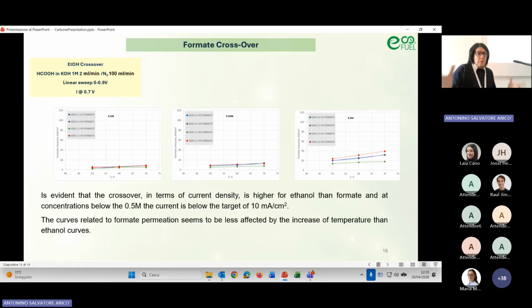Because some partners also found formate in the liquid stream collected by the test, a formate crossover was also measured in the same way as the ethanol crossover, and we can see that the crossover in this case is very, very low and is below the target of 10 milliampere per square centimeter up to 0.25 molar.